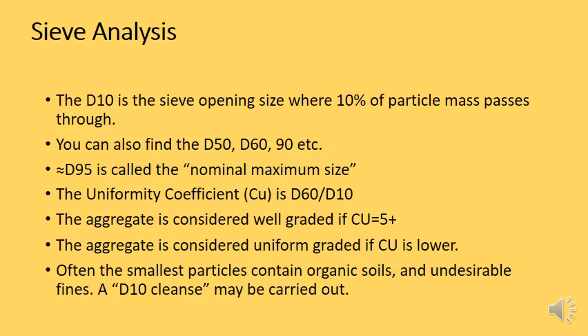Now, there's something called the D10. The D10 is basically the sieve opening, or the hypothetical sieve opening, where 10% of the particle mass will pass through. So any particle that falls below this 10%, it means it's the 10% of the total mass of the aggregate, which is smaller than the other 90% of the aggregate. That's what the D10 is. It's the 10% diameter. You can also find the 50% diameter, where half of the aggregate is smaller than this diameter and half is bigger than this diameter.